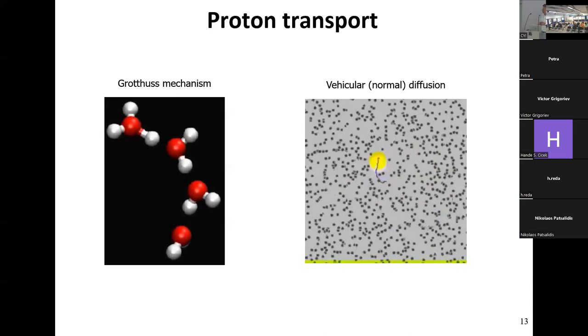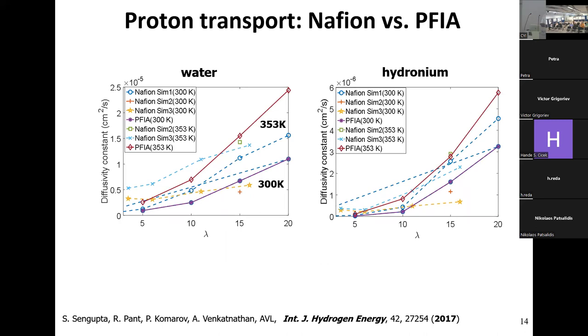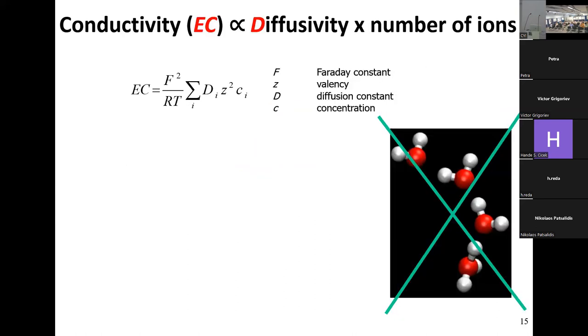We measure translational mobility via mean square displacements of ions and water, then extract diffusion constants for water and hydronium at different temperatures. Dashed curves are for Nafion, solid curves for PFIA. Diffusion coefficients are very close between the two materials across hydration levels. Hydronium diffusion is about an order of magnitude slower than water diffusion because it is charged and trapped by sulfonate groups.